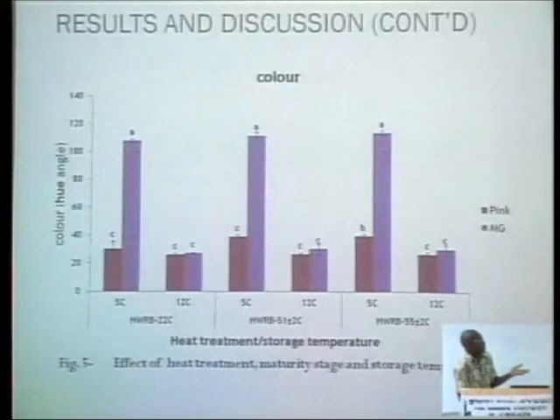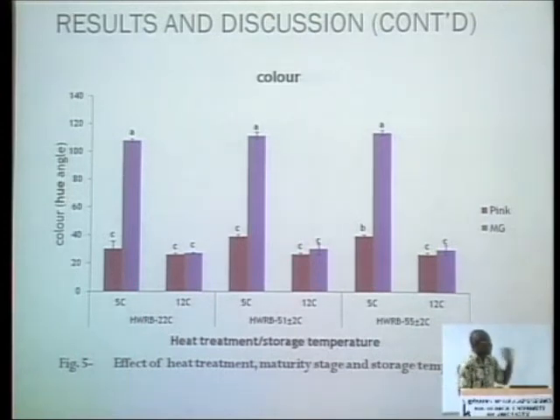the color, when we did the student t-test, we noticed that there was significant difference between the heat treatment on color. And the inhibition was much higher at 55 than at 51. And one thing we should know is that color also plays a very important role in the ripening, because as fruits ripen, they change color. So the color is an indication to tell us whether the fruit is ripening and whether it's deteriorating very fast. So if we're able to inhibit color change at a certain temperature, then it means that we can prolong the shelf life of the fruits. And the heat treatment was able to do that for us, especially in the mature green than in the pink. Okay, thank you.